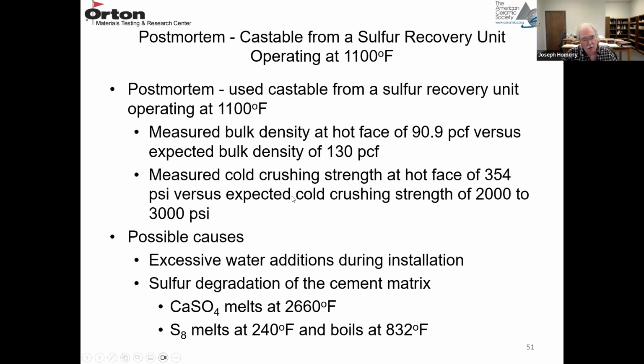So what could have caused that? Well, you're always suspicious about the amount of water that was added during installation. If too much water is added during casting of a castable, it's less dense and weaker because of the higher porosity concentration. Probably not a real problem in this failure analysis, but the sulfur is degrading the cement matrix. So it's reacting with the calcium to form calcium sulfate. That has a pretty high melting temperature, 2660 degrees F. But the elemental sulfur S8 melts at a pretty low temperature and boils at a pretty low temperature.